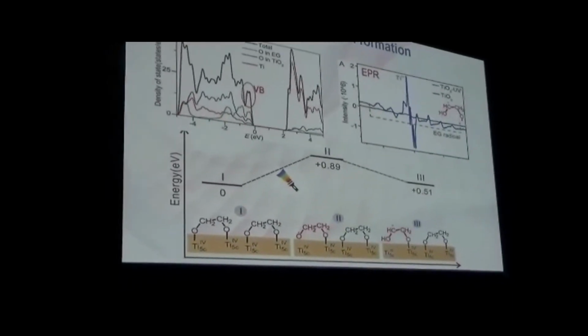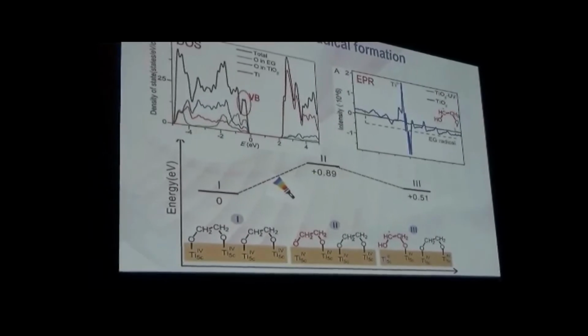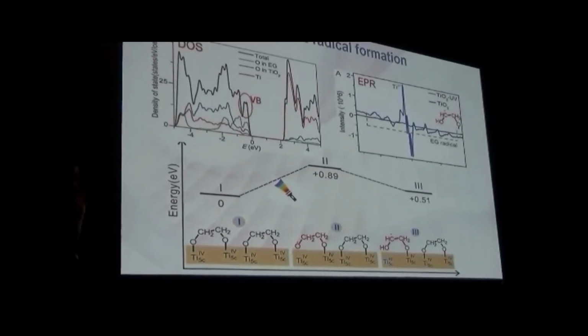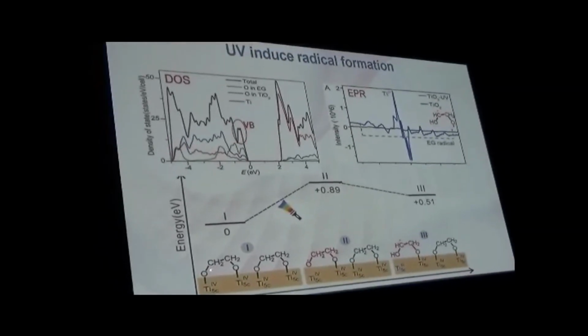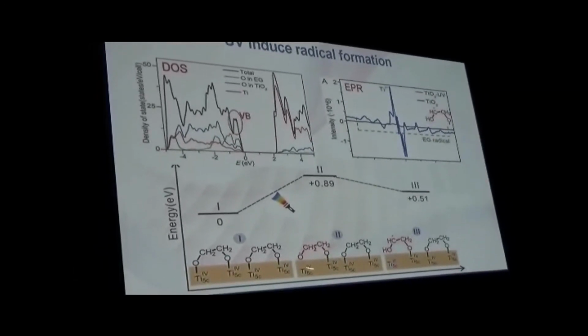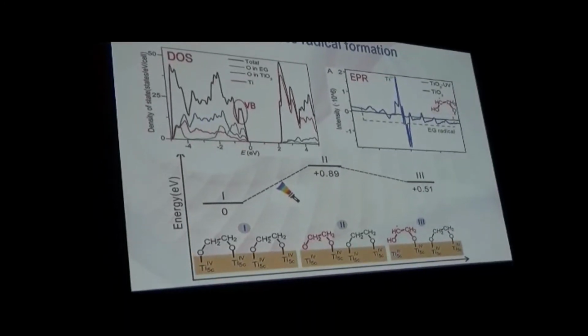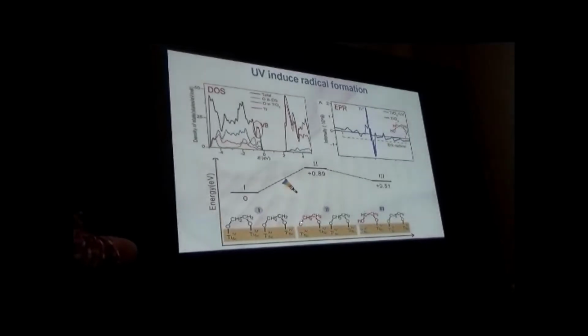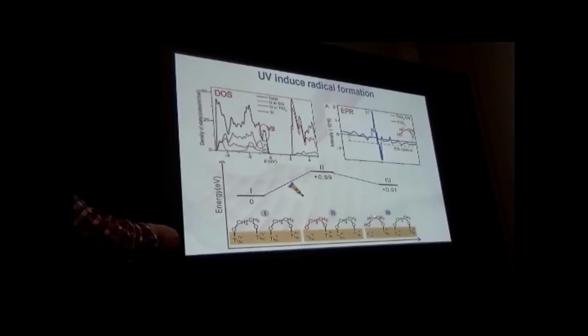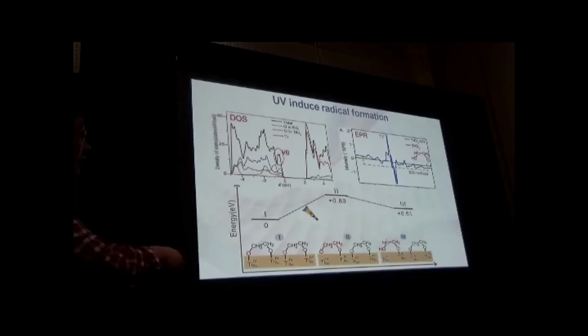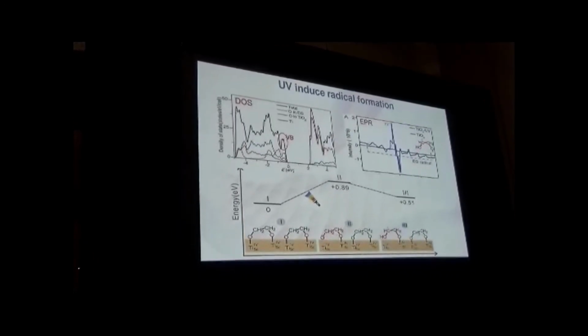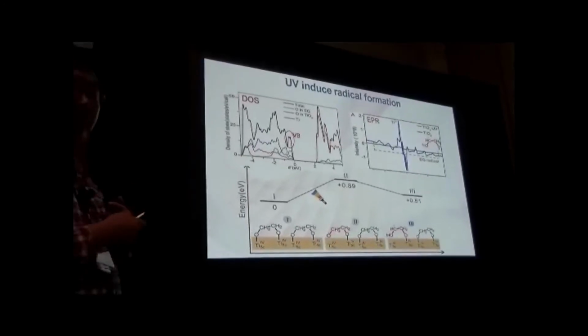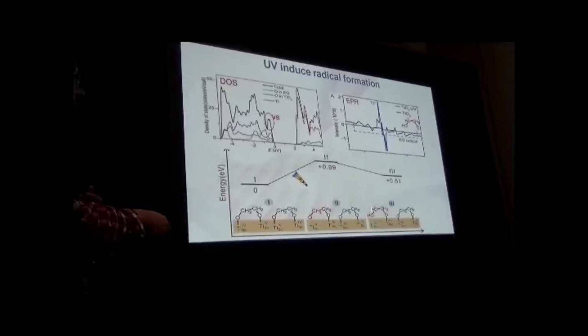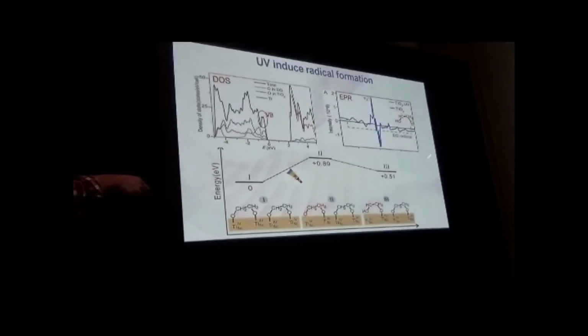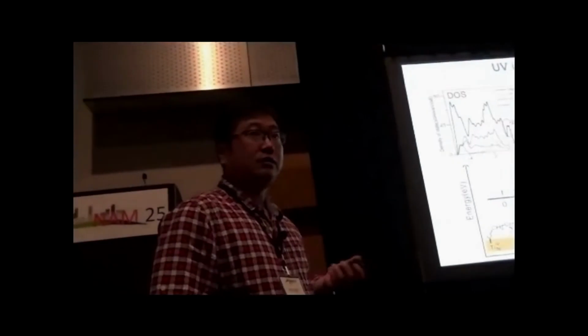Upon UV irradiation, the electron and the hole will be separated. The electron will go to the titanium, and the hole will go to the oxygen to make an oxygen radical. Because the oxygen radical is less stable than the carbon radical, it undergoes a hydrogen transfer to make a carbon radical. Yes, because UV induces radical formation. This feature has been confirmed by EPR. You can see this picture is the ethylene glycolate radical. We have confirmed this.